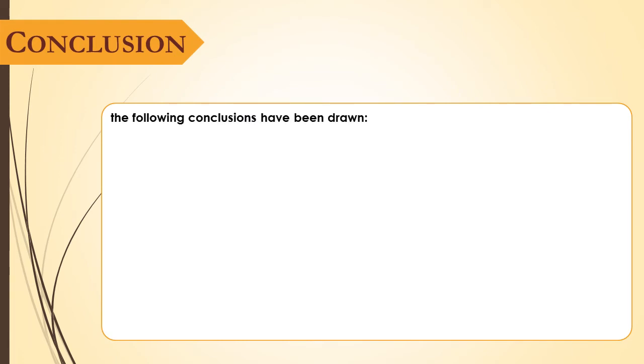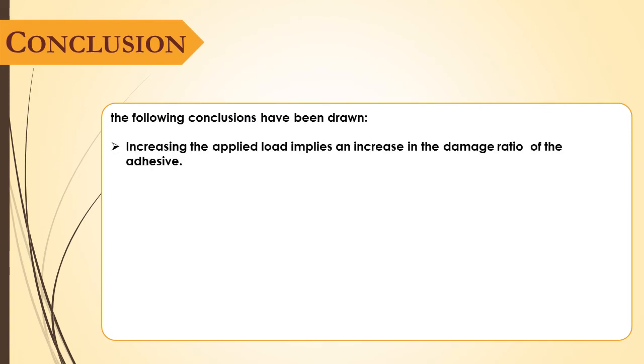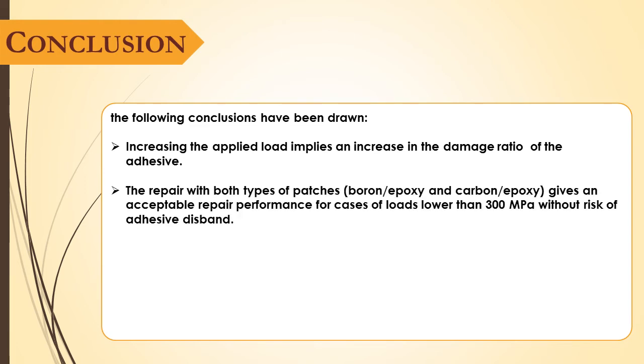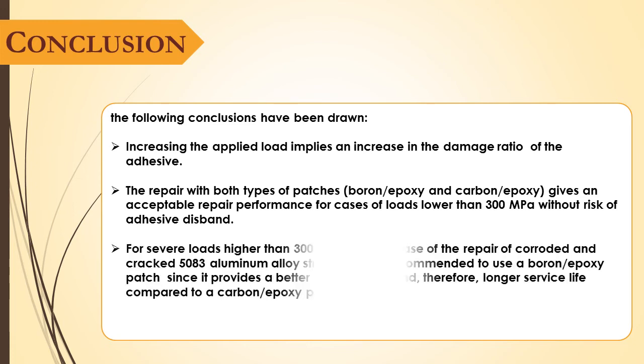The following conclusion has been drawn. Increasing the applied load implies an increase in the damage ratio of the adhesive. The repair with both types of patches, boron epoxy and carbon epoxy, gives an acceptable repair performance for case of load lower than 300 megapascal without risk of adhesive disbond.